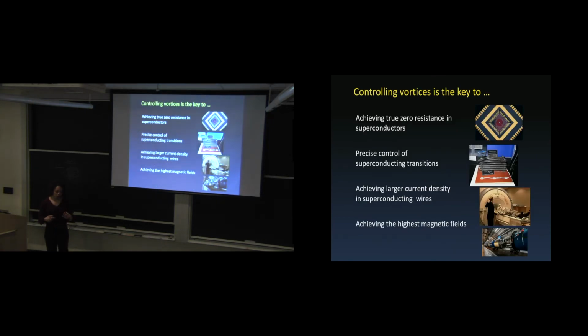Okay, and why do we care about vortices? Well, we care about vortices for the same reason we care about superconductors. We want something that's zero resistance. Vortices prevent it from being zero resistance. And so, if you want to have a detector or wires or have large current density in a magnet, for example, achieve the highest magnetic fields, the biggest challenge is understanding how the vortices penetrate, right? The reason that MRI magnet wire is limited the way it is because vortices start penetrating into the wire itself. Okay, so understanding and controlling vortices is key to really achieving the best superconductivity.